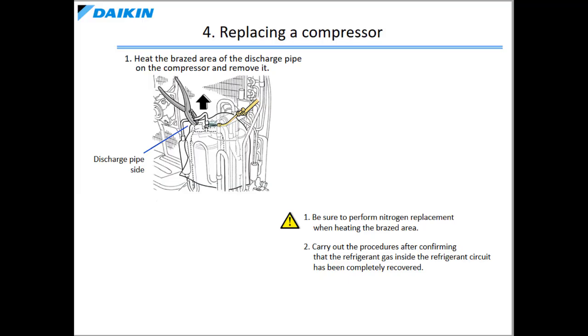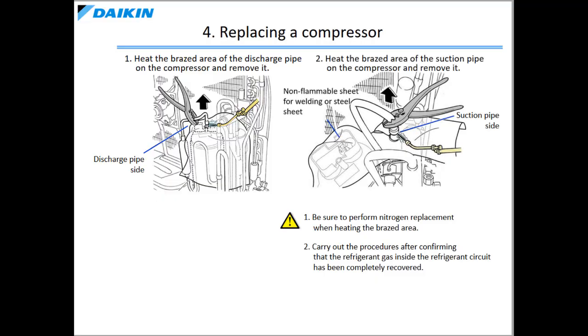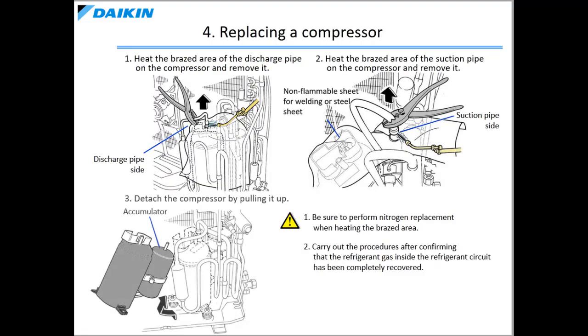Be sure to confirm that the refrigerant gas inside the refrigerant circuit has been completely recovered before heating the brazed area with a welding torch. While performing nitrogen replacement, heat the brazed area of the discharge pipe on the compressor and remove it. Heat the brazed area of the suction pipe on the compressor and remove it. Finally, detach the compressor by pulling it up.